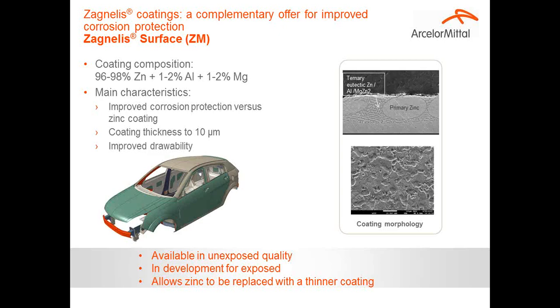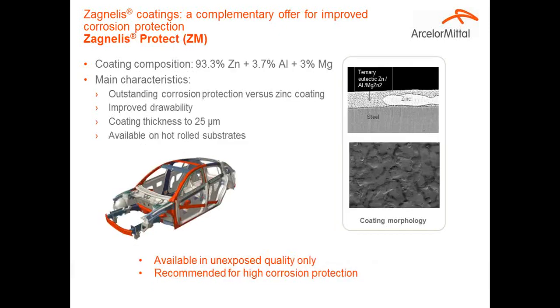Zanilis Protect has outstanding corrosion protection properties. It has so much that we can recommend it to replace thick GI coatings. It has an improved drawability. We are offering coating thickness up to 25 microns, and it's also available on hot rolled substrates. It will be available for unexposed only, and we recommend it for high corrosion protection.